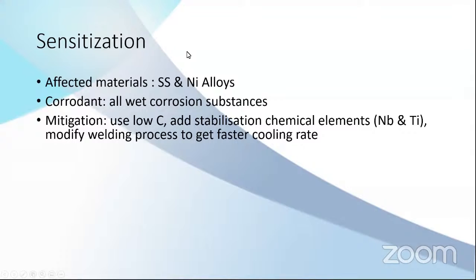So this sensitization is the reaction between carbon and chromium in the stainless steel or nickel-based alloys. So one of the mitigation methods is to use lower carbon, or to add stabilization chemical elements, either niobium or titanium. This takes carbon easier than the chromium. So when you add this, it reacts first with the carbon, so the chromium can stand by itself. It doesn't react with the carbon. Or if you don't have any choice, then you have to modify the welding process to get a faster cooling rate, so that there is not enough reaction for the chromium and the carbon to react.